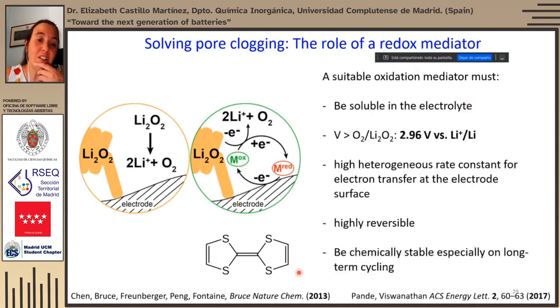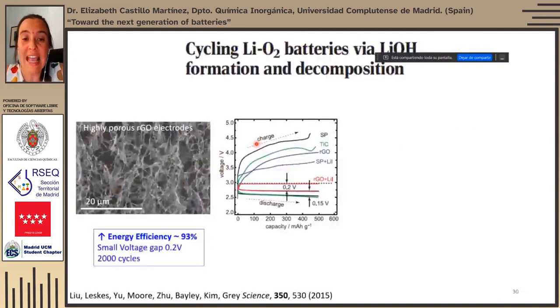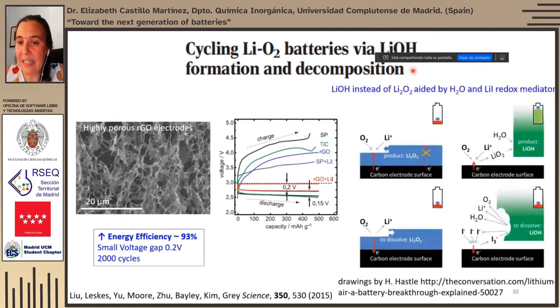So it is important that the redox mediator is soluble in the electrolyte, that it has an oxidation potential above the oxidation potential of the lithium peroxide that we want to oxidize, and of course that this reaction is fast enough. A breakthrough in lithium-air batteries came in 2015 in the group of Professor Gray, when they used highly porous reduced graphene oxide electrodes, as well as a lithium iodide redox mediator and some unwanted amount of water, unwanted at the beginning, but then wanted and controlled, in which actually, instead of forming lithium peroxide, it formed lithium hydroxide. If we form lithium hydroxide, we are getting 4 electrons per oxygen molecule instead of 2 electrons, and the capacity can be increased further.